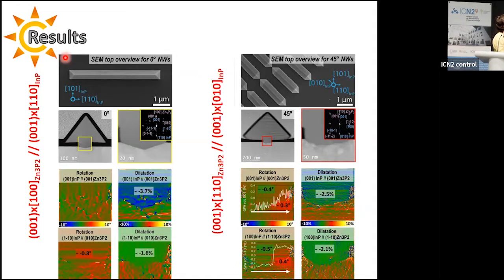As we can observe in both cases, from the image crystal quality point of view, from the power spectrum analysis, we can observe that the zinc phosphide is highly crystalline, growing epitaxially on top of the indium phosphide as it follows the same growth direction. The only difference is related with the interface between the nanowire and the substrate, because in this case, it is much more rough than in this other case where it's sharp. And this is related to the size of the aperture of the trenches and the mutual distance one to the other.